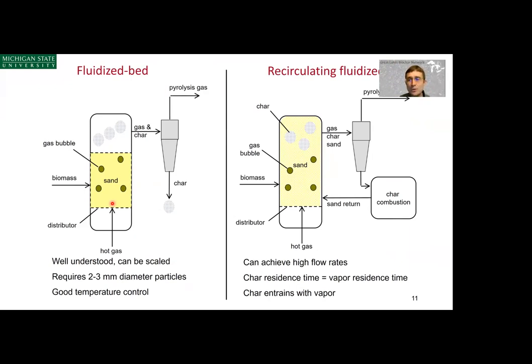The sand serves as a heat transfer medium, rapidly transferring heat to biomass on the order of perhaps 1,000 degrees Celsius per second. What happens is you create pyrolysis vapor and biochar.